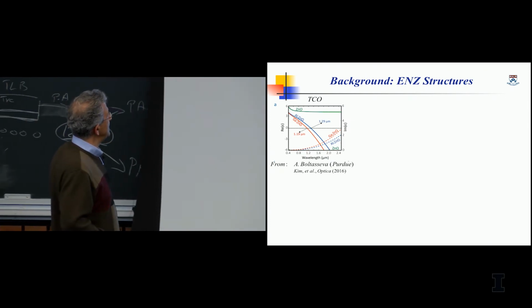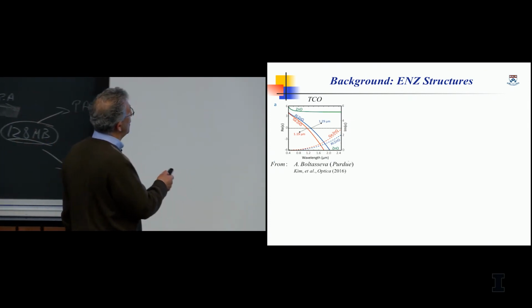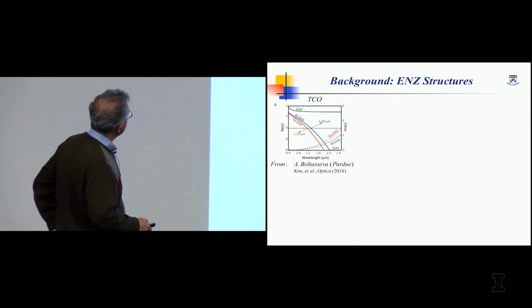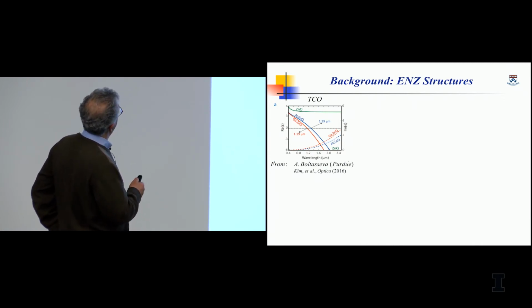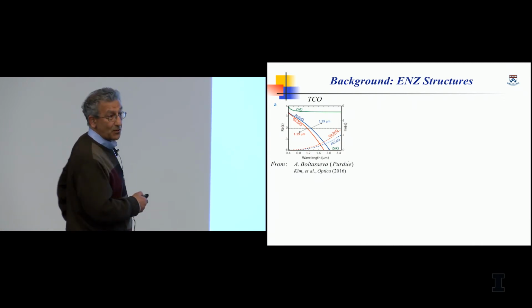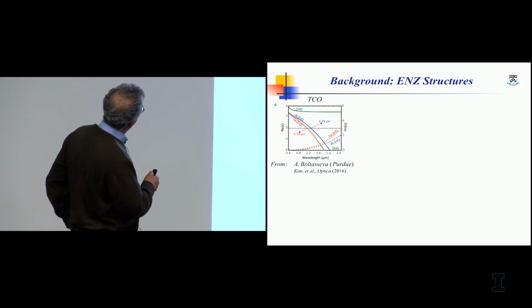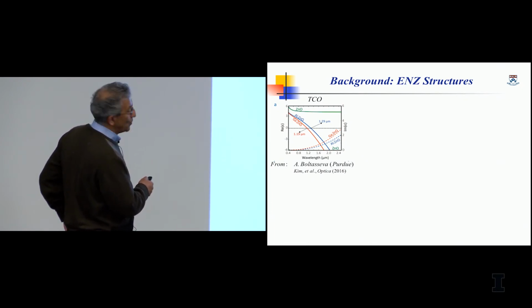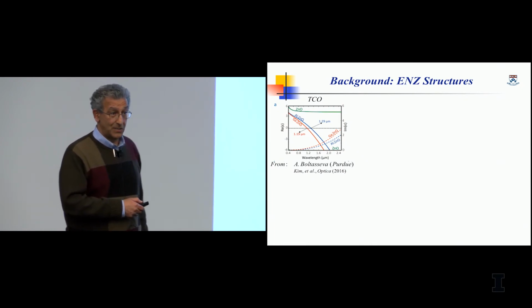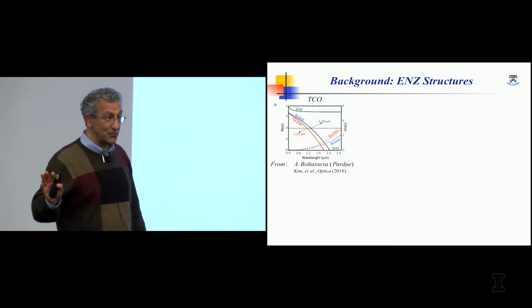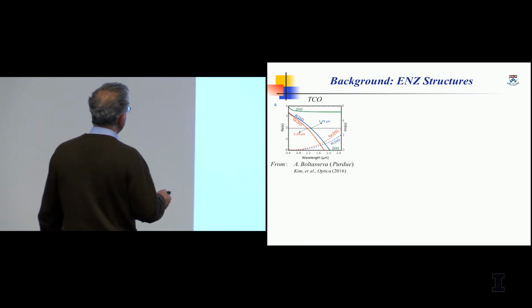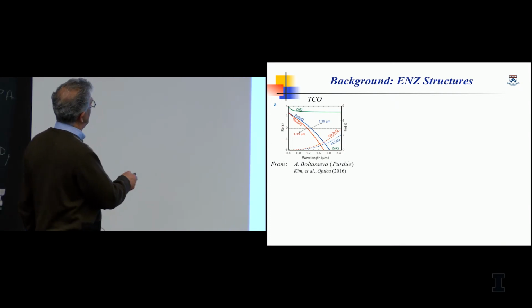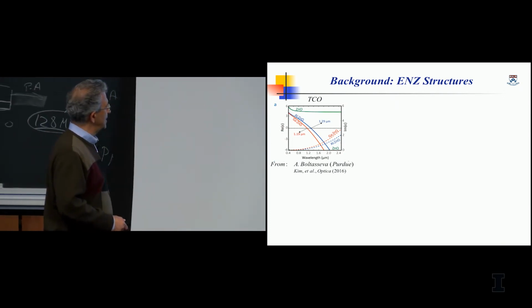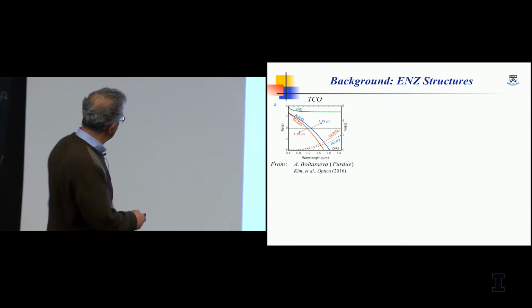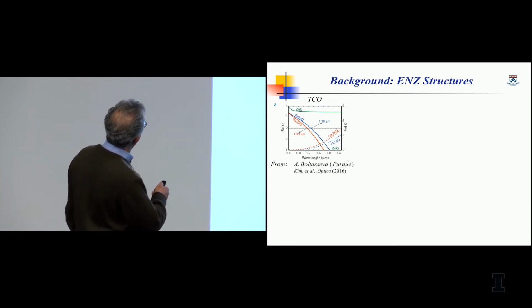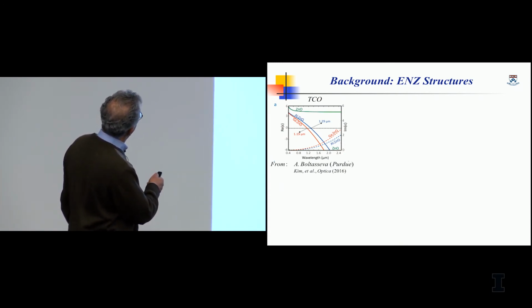For example, in the near IR, transparent conducting oxide, indium tin oxide, aluminum doped zinc oxide, gallium doped zinc oxide, they have a 0 crossing at about 1 to 1.2 micron. That's close to telecommunication wavelength that we have there. This is a result, by the way, this experimental result obtained by my collaborator, Sasha Boltasseva from Purdue, that we actually have a paper together in this regard. And indeed, you see that these are the 0 crossing of this.